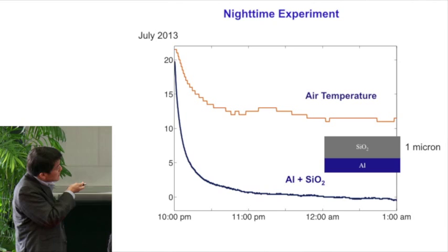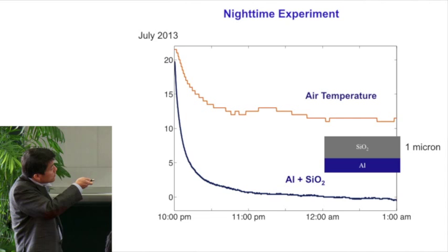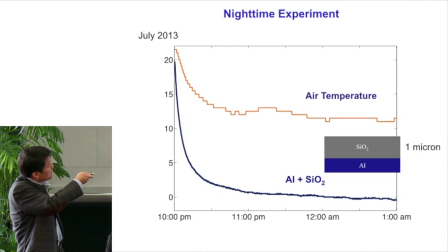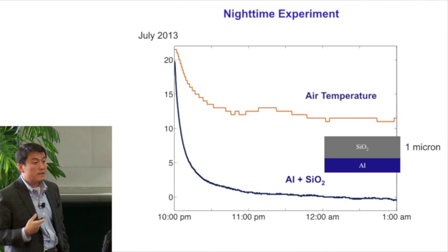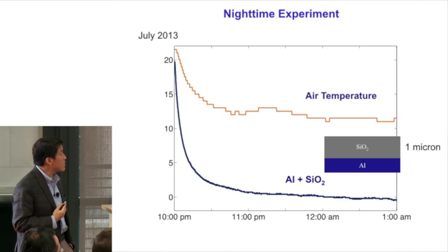Here are some initial experiments where we tried to reproduce some of the nighttime experiments that people have done before, but with a very simple structure of silicon dioxide on aluminum, on a cool summer night where the ambient air temperature is about 13 degrees Celsius. This thing very quickly gets to freezing. That, of course, is at night, but it says that you can really cool things down by radiation. Daytime is quite a bit harder.